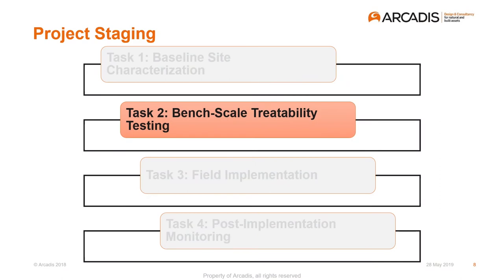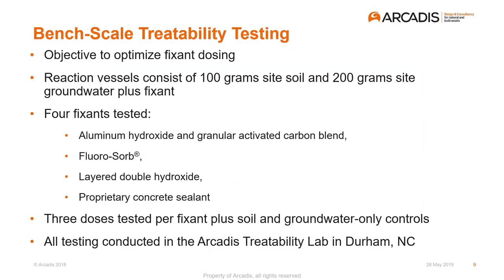All right. Switching more to the treatability testing. So we took that soil, took it into the lab. The objective was to optimize the fixant dosing for the field, so not unlike a vial study ahead of a column test. We did some bench testing to pick what concentrations of fixant we were going to take to the field for the test pits. The reaction vessels were approximately 100 grams of soil, 200 grams of water. We tested 4 fixants, one of which was FLUORO-SORB.